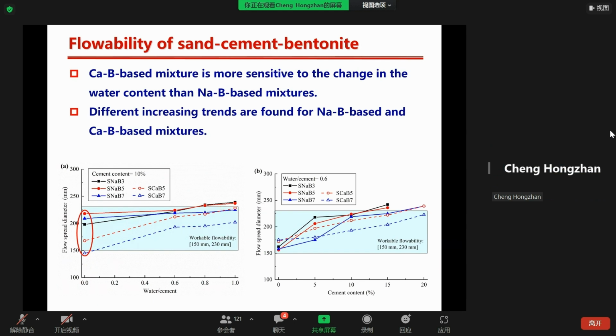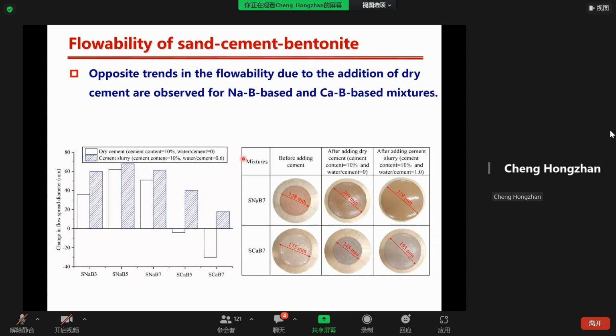Interestingly, there is a significant difference in the flowability for these 2 types of bentonite mixtures, and as shown in the right figure, the flow diameter of the mixture increased with the cement content. To better characterize the effect of cement slurry, the left figure compared the change of flowability caused by adding dry cement and cement slurries. Based on the dry cement result, we can find opposite changes in the flowability for the 2 types of bentonite. For sodium bentonite mixture, the flowability increased, but for the calcium bentonite, the mixture flowability decreased. This can be clearly seen from the photos of mixtures after the flow table testing.